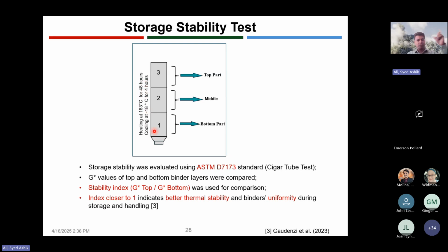Then we took it out and directly put it into the freezer at -18 degrees Celsius for 4 hours. After these 4 hours, we took the cigar tube out, marked it into three equal divisions, and then cut the cigar tube into three parts. And then we conducted the DSR test on both the top part and also the bottom part. From the dynamic shear rheometer DSR test, we found the G star value for the top and bottom, and then used the ratio of G star of the top and bottom sample as a stability index. This index was then used for comparison purposes.